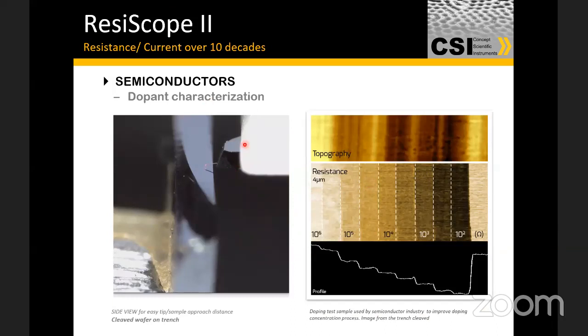And here's just some more illustrations. If you want to make a dopant measurement, you can do that too, across the section of the sample surface. And this is a nice feature that we have on the Nano Observer, that we can view the cantilever and the sample environment from the sides as well. It allows us to make these cross-sectional measurements on semiconductor samples a lot easier.